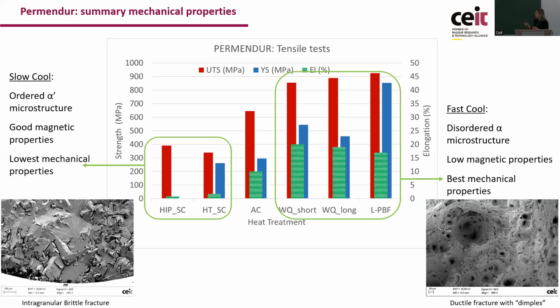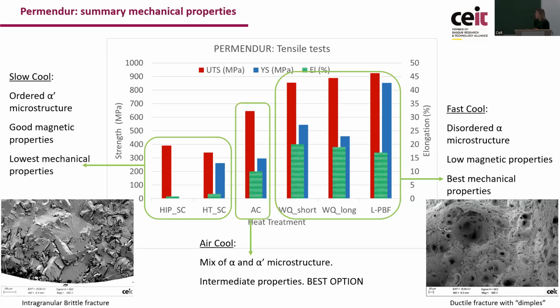On the other side, if we do a very slow cooling rate, we have a material that has an ordered alpha prime microstructure with very good soft magnetic properties, but we lose completely the mechanical properties. So for the Addimot project, what we needed, and what were finally the optimized conditions, were the ones that were intermediately cooled, so with air cooling, where we obtained a mixture of microstructures that gives us enough magnetic properties for the application and also enough mechanical properties for machining and also for the application itself.